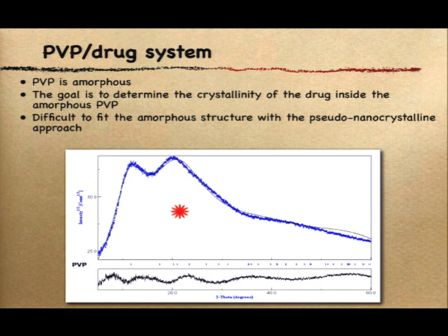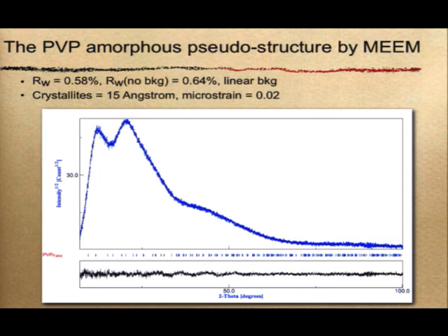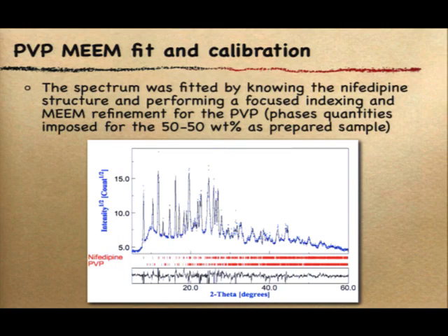Here we will see later, we want to characterize two amorphous phases, okay? So we need to get the best we can. We decided, okay, we don't care about the structure, so we use the Pawley way, okay? And actually, instead of just fitting some experimental structure factor, like Le Bail, I prefer to extract an electron density map and use that one, just so I'm more sure I can compute every peak or whatever. But it's simply the same. So I could get, you see, a very good fit using a map sufficiently big to fit this one.